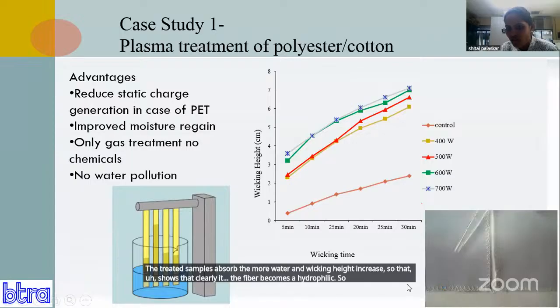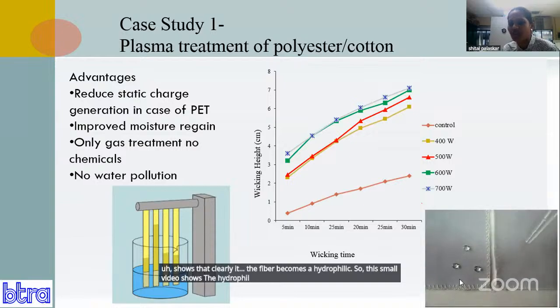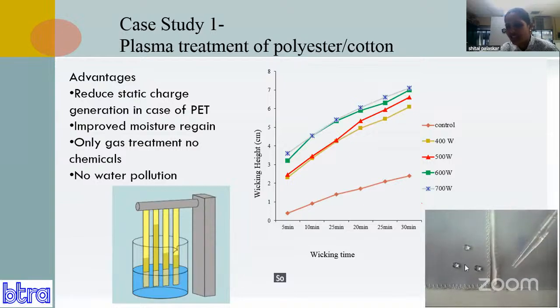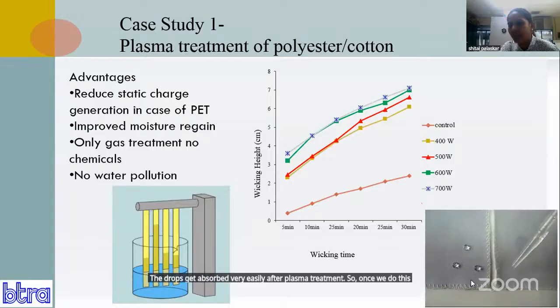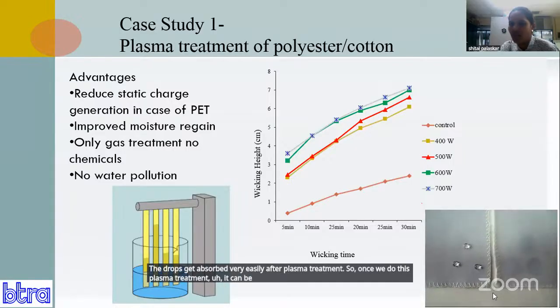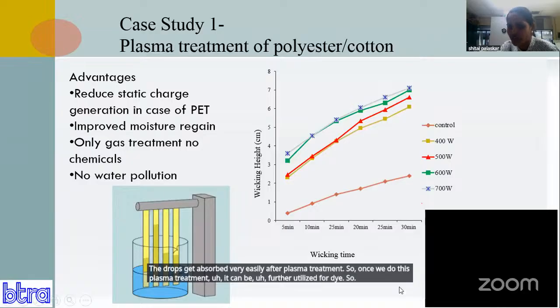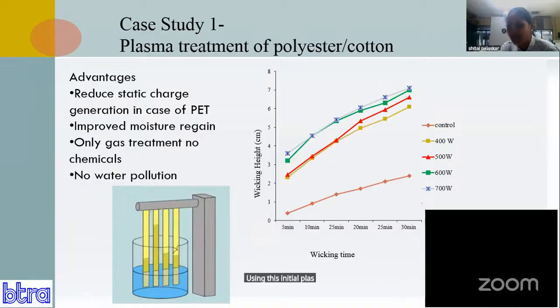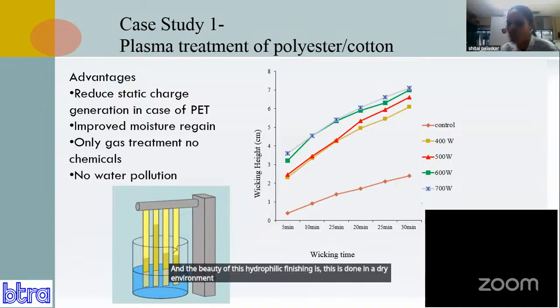So this small video shows the hydrophilic finishing of the polyester fabric. This is the initial fabric and this is after plasma treatment. You can see here the drops get absorbed very easily after plasma treatment. Once we do this plasma treatment, it can be further utilized for dyeing. Dyeing can be improved using this initial plasma treatment. Printing can be improved using this plasma treatment. And the beauty of this hydrophilic finishing is that it is done in a dry environment. Only gases were used, no water, no chemicals.